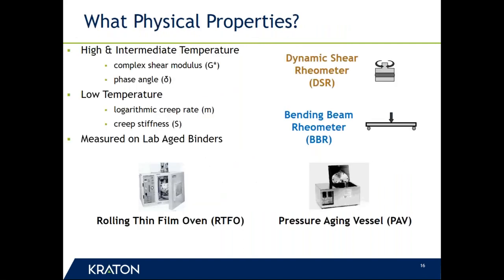The physical properties that are tested, instead of pushing stuff through a tube and timing it, or letting it flow through a tube, or sticking a needle in it, what you're doing these days is something which, I like to say, is analogous to a high-tech heel test, or a power steering turn test, where you're applying a shear load, but you're monitoring the response, and then you're taking the response to that load along with the amount of load applied, and you're able to determine characteristics from that that are rheological characteristics or flow-based characteristics that can be related to pavement performance. The dynamic shear rheometer is that test, and that's sort of the backbone of this system.